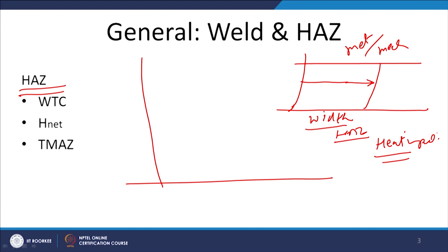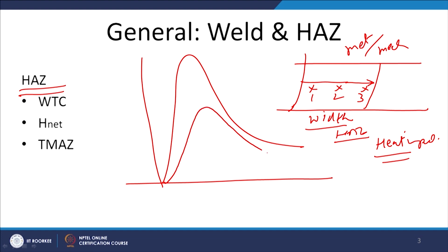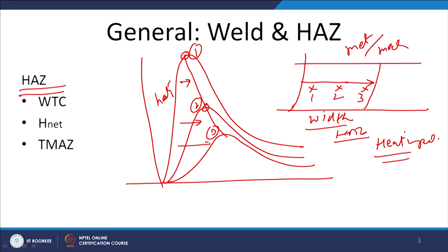So, in the HAZ, if we take 3 different locations 1, 2, 3, then each location will be showing us a different weld thermal cycle, which means different peak temperatures and different cooling rates. So, heating rate is high for point 1, then point 2 and point 3. We will see that peak temperature is decreasing and it is taking longer time to reach the peak temperature. That is what we can see, the shift towards the right. This is the time scale and this is showing the temperature, and this is what is typically called the weld thermal cycle.